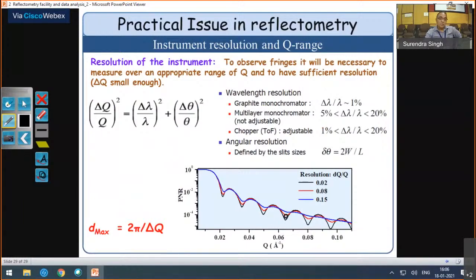When we increase delta q by q, that means we are making poorer resolution for the instrument. Then these oscillations smear down, so the features are not so sharp when you have poor resolution.